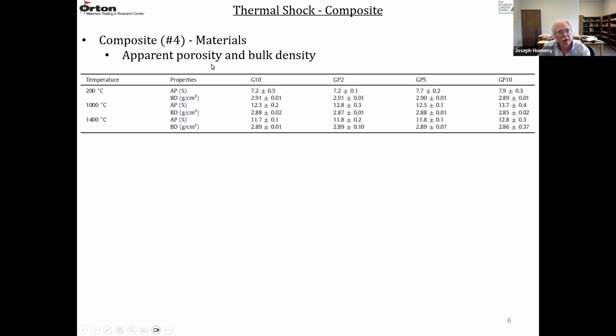So this is the density and porosity after curing the resin and then coking at 1000 and 1400 degrees C. AP is apparent porosity, BD is bulk density in grams per cubic centimeter. So they have here G10, then GP2, GP5, and GP10. After curing the resin, the porosities are all 7 point something, so between 7 and 8. The bulk densities are very close to about 2.9. So adding the pellets didn't really affect the density.